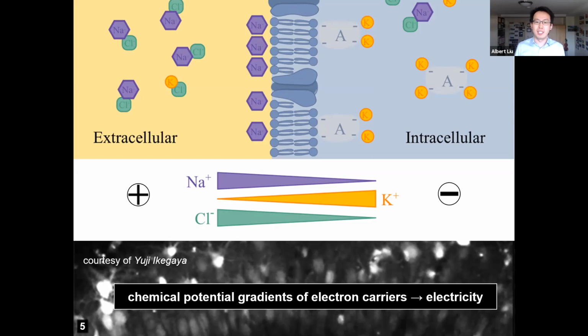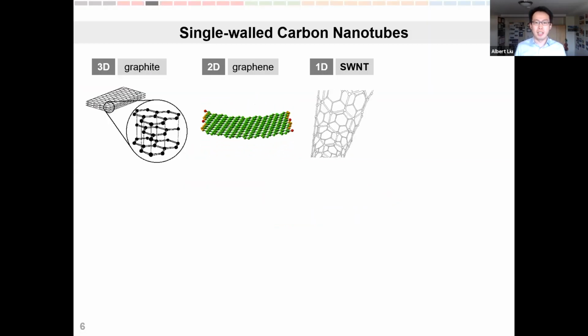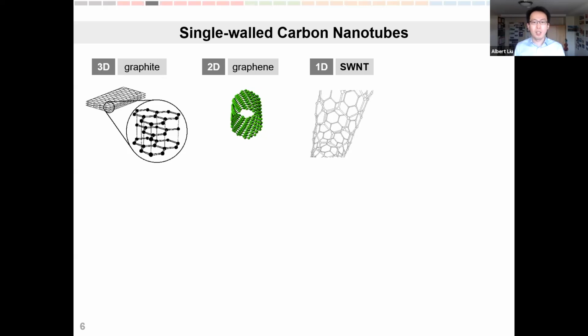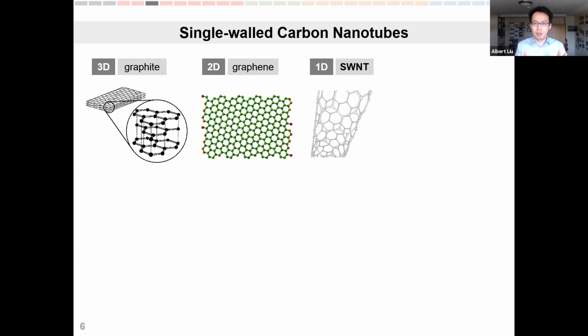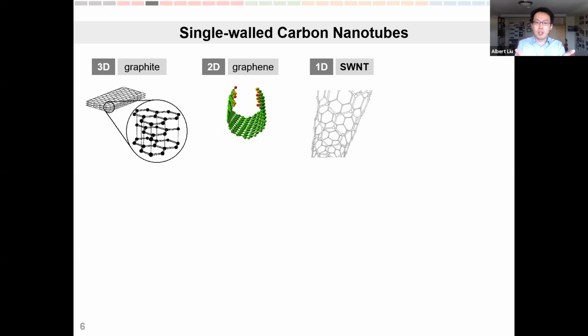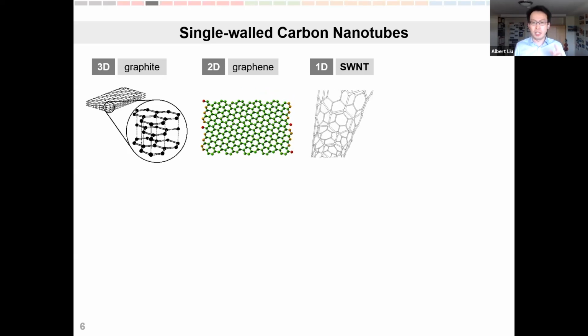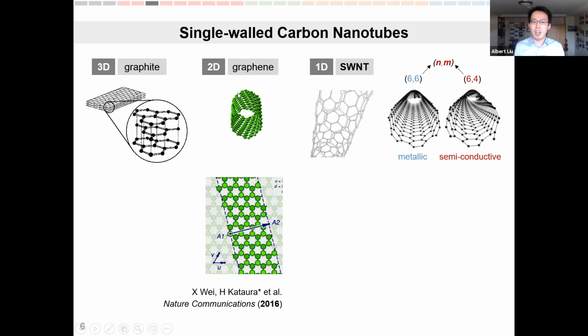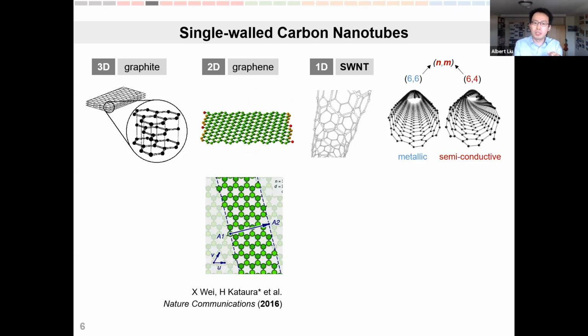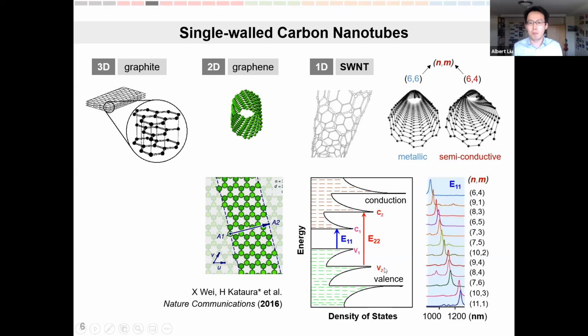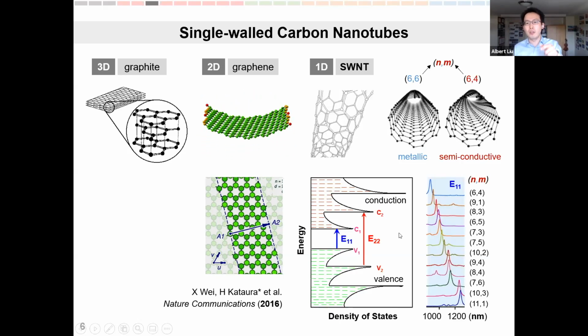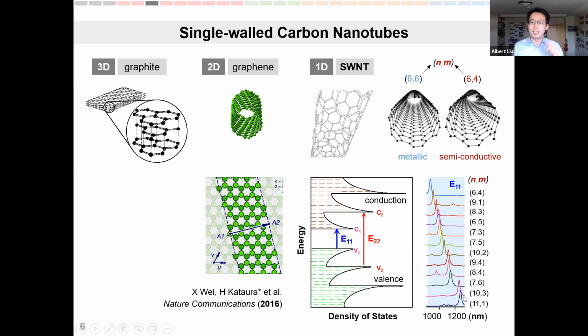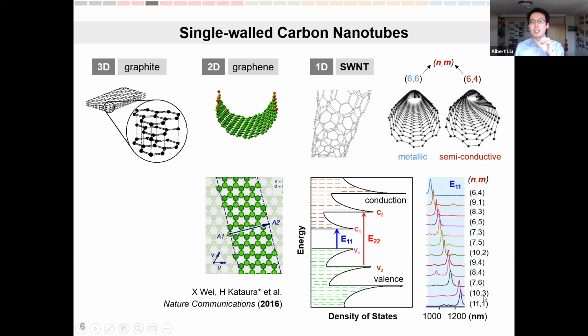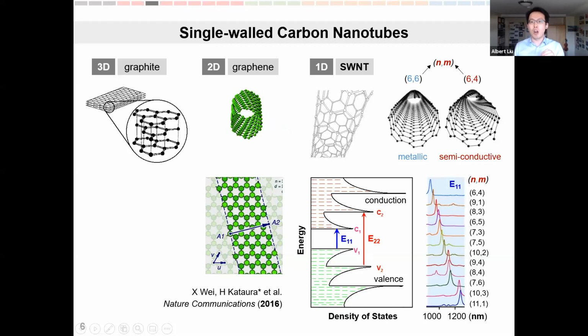So first and foremost, we have to select the material. The material of choice here is single-walled carbon nanotubes. For those of you who are not familiar with carbon nanotubes, you can roughly think of them as rolled up sheets of graphene. And graphene itself is, again, a two-dimensional atomic layer of carbon. The interesting thing about carbon nanotubes is that depending on how you roll up your sheets of graphene, you get different electrical properties and different electronic band structure. And that corresponds to different optoelectrical properties of the carbon nanotube. So this idea that we can very carefully tune the electronic structure and band gap of carbon nanotubes with different chirality renders this material very, very powerful.